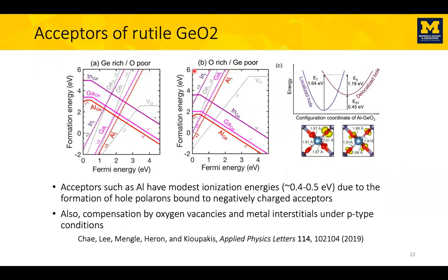We also look at acceptors. And now you see easier the ionization energy. If you look at the energy difference between this level here and the valence band, that's the energy you need to pay to ionize the holes. Again, these act as acceptors. So the acceptors are not too deep. The problem is they are compensated. As you go towards p-type conditions with your Fermi level closer to the top of the valence band, your aluminum atoms, let's say, won't replace germanium. Instead, they will become interstitials. You're also going to form oxygen vacancies, and all of these defects steal the holes, and so you won't get p-type conduction.